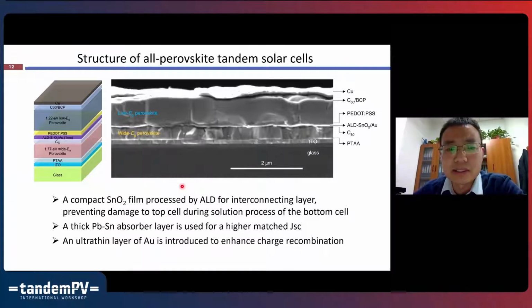And this ITO layer is very conductive, and it will also not be good for the monolithic integration when you want to make the modules. And also the ITO layer is not very optically transparent, especially in the infrared, near infrared spectral region. So by replacing this ITO layer with the compact tin oxide layer, we can also make the second perovskite layer on top of it, the wide bandgap subcell, without any damage.